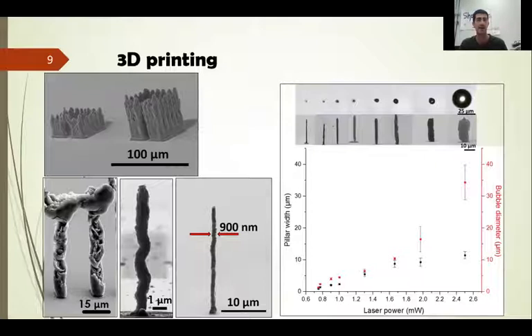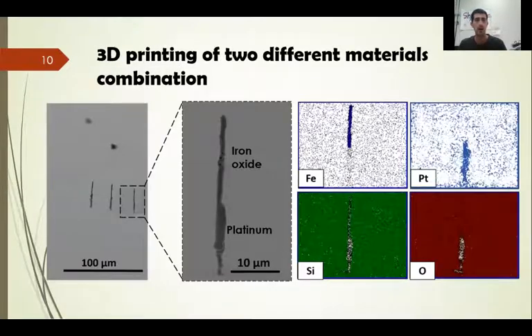The last result that I want to share with you is that we also succeeded to combine two different materials in the same structure. We made some pillar with a base of platinum and top from iron oxide. This result is very unique compared to the other 3D printing techniques.